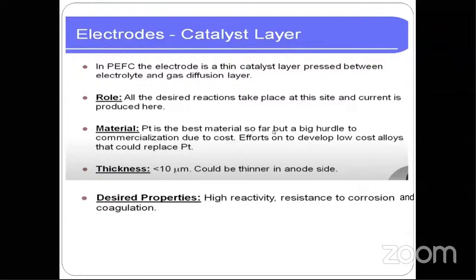Then if you see the catalyst layer in a PEM fuel cell, the catalyst layer is very thin. Okay, it is in between the electrolyte and the gas diffusion layer that I have shown in the video as well as the previous slide. The role: the desired reactions take place at this site and current is produced. So for the materials, basically platinum is the best material for this catalyst layer. But the problem is that platinum is very costly and available only in some countries.